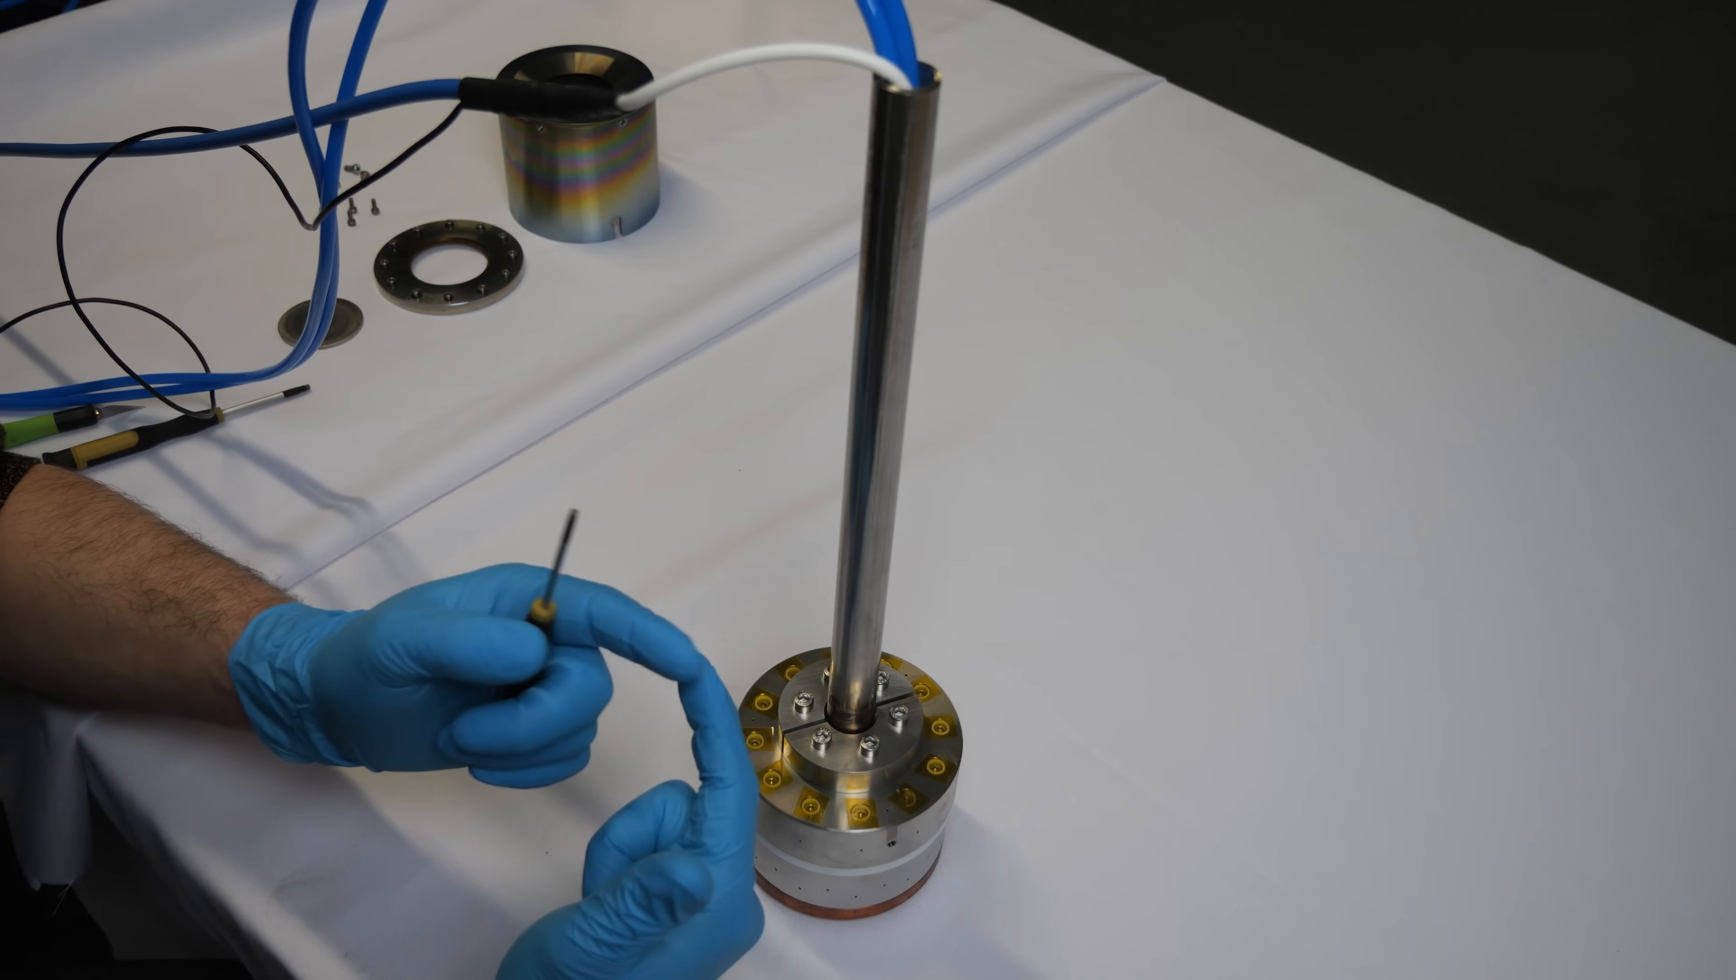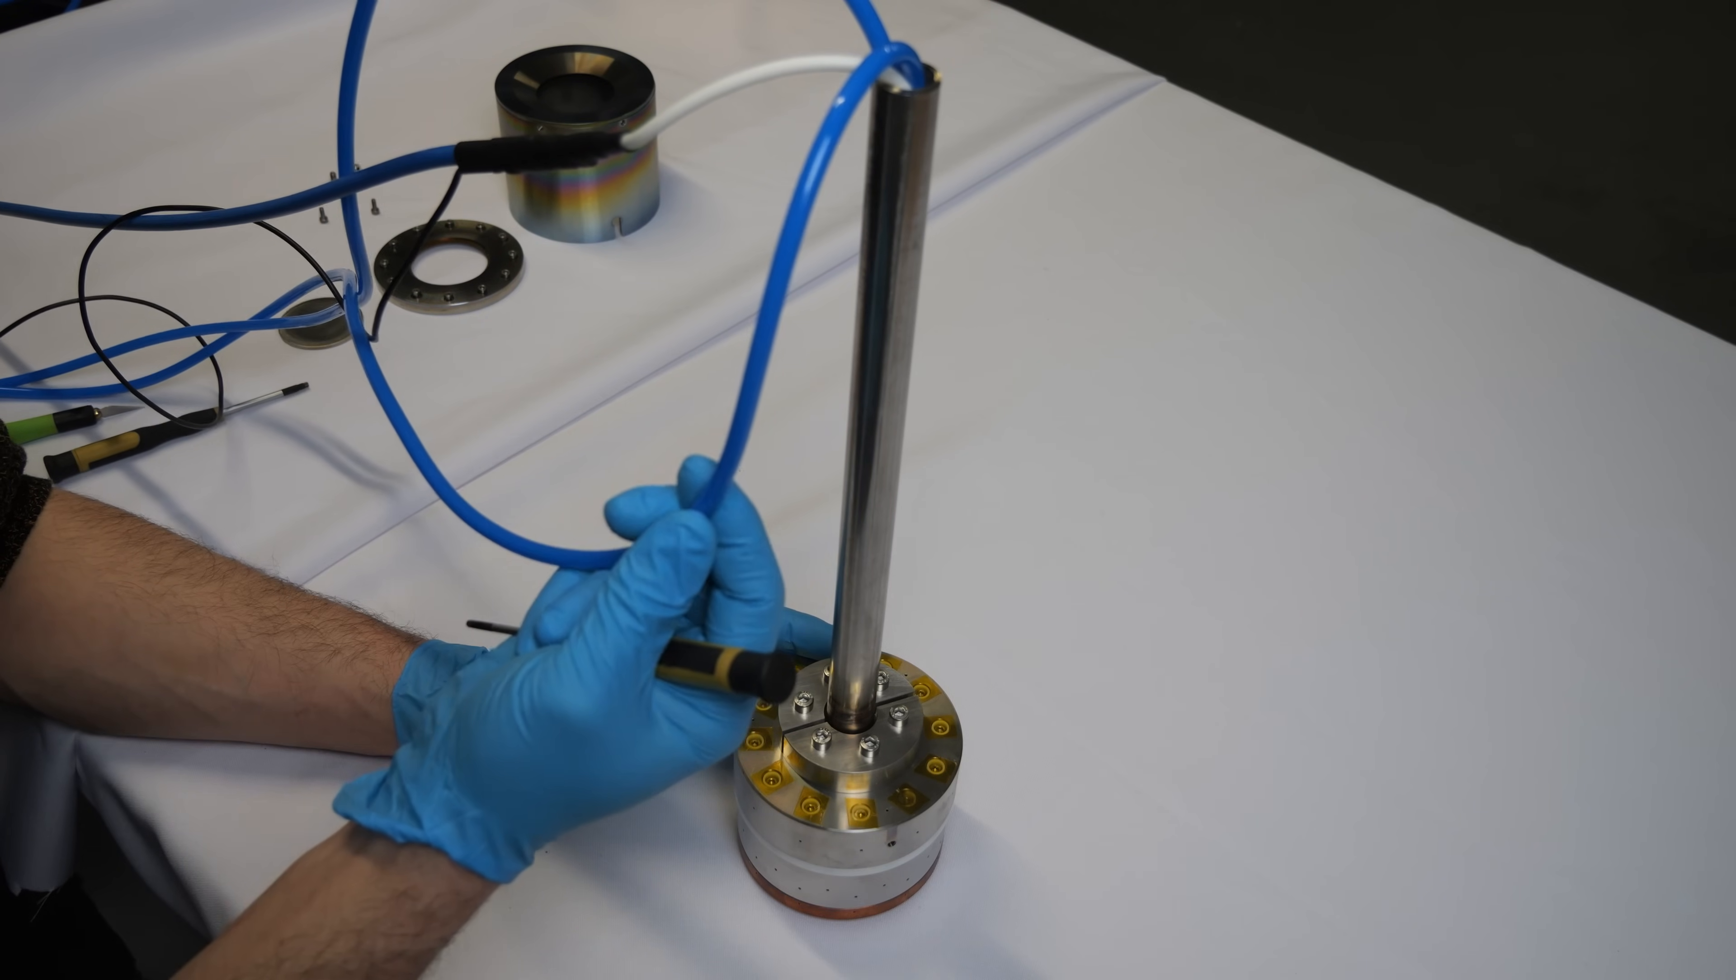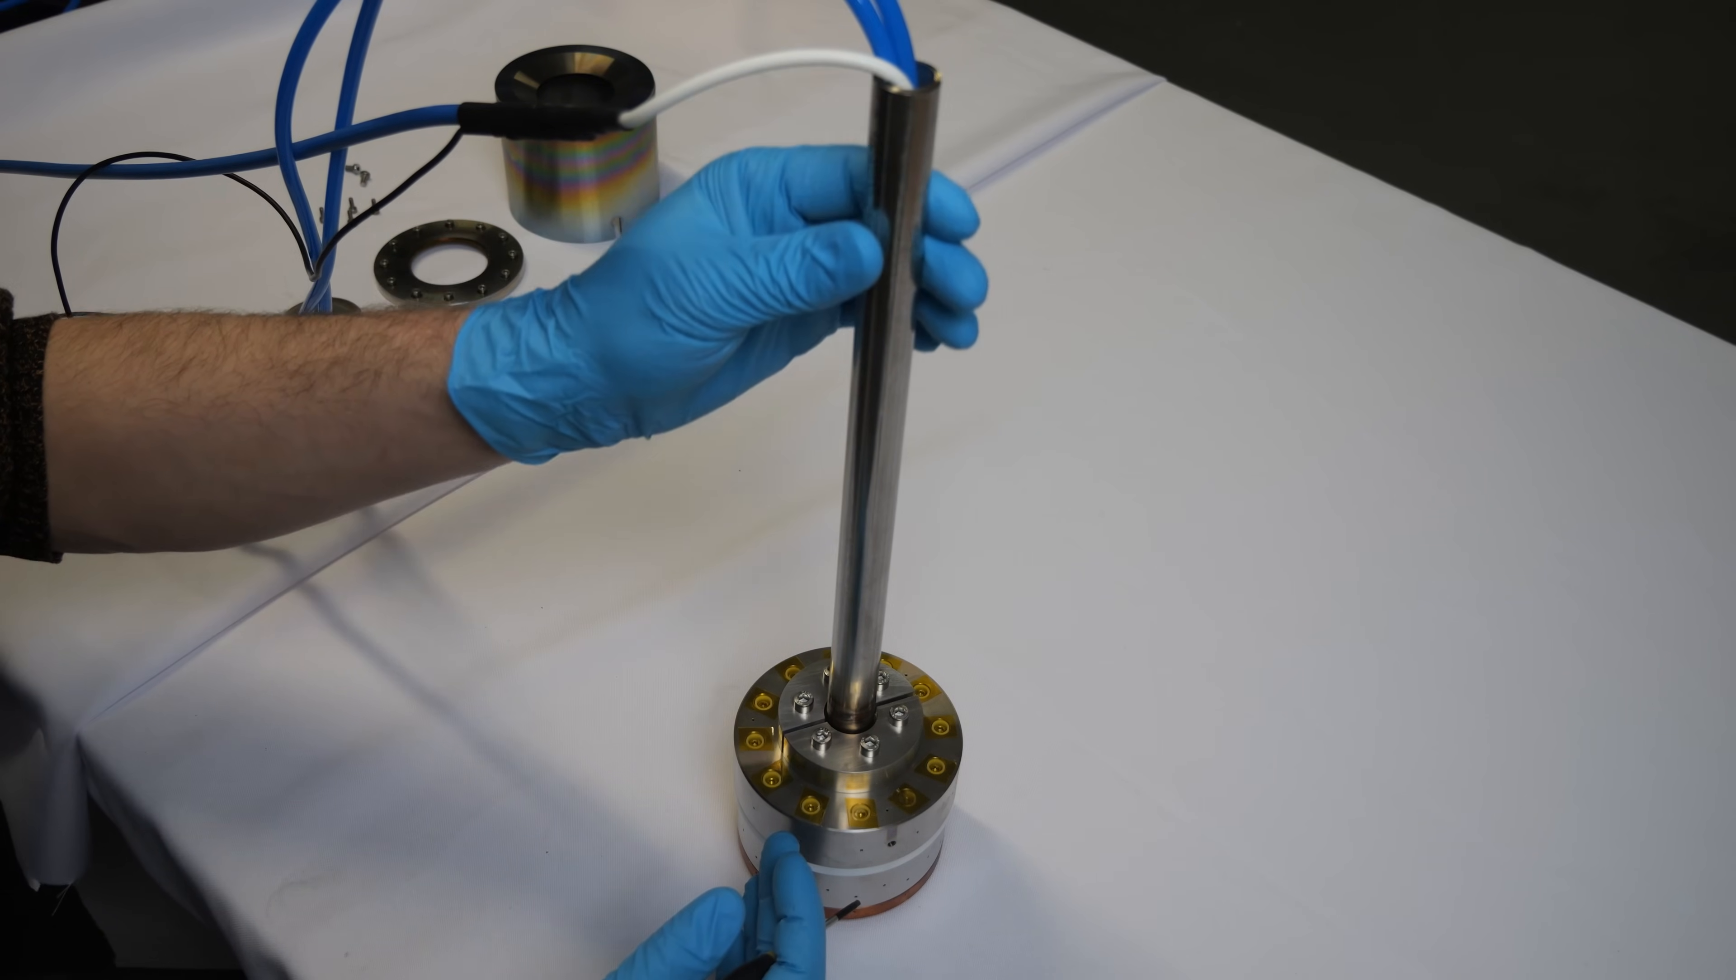Both of their designs had the cooling water tubes and also the high voltage cable exposed to the vacuum which has two consequences. On the one hand you need two feed-throughs for your water cooling and you need another feed-through for your high voltage. It also means that the plastic from the water cooling tubes and your high voltage cable is exposed to the vacuum. So if you're using for example a plasma cleaning setup you will over time erode your plastic hoses and contaminate your vacuum, and water will slowly saturate the plastic from the hoses and diffuse in your vacuum.